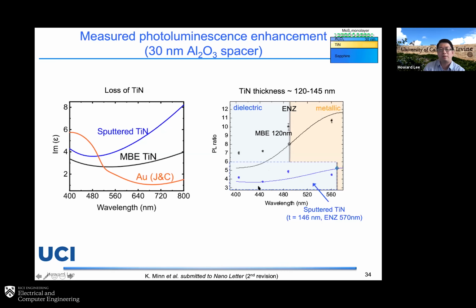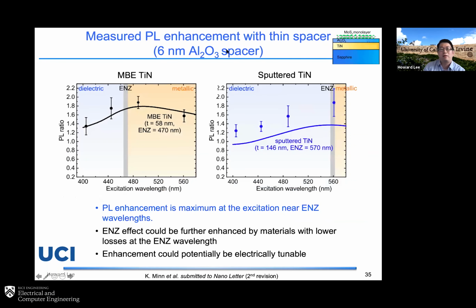And the losses here play a quite big role as well. So if we go to the lower thickness, like 6 nanometer, for the MBE titanium nitride and sputter titanium nitride, you can see that this is an ENZ wavelength. You have a peak of the PL enhancement really close to the ENZ wavelength. So clearly you can see that you have an enhancement due to the ENZ effect here.